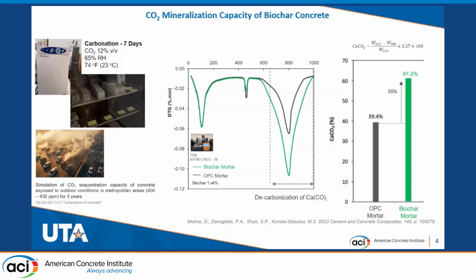And we assessed the carbon mineralization capacity. We followed this carbonation regime, this exposure concentration of CO2, to mimic the CO2 sequestration capacity of concrete exposed to outdoor conditions in metropolitan areas for approximately 3 years. And the CO2 sequestration was assessed through TGA tests. Using the weight-temperature data from a TGA test, we determined the percent amount of calcium carbonates by quantifying the weight loss between the temperatures of 525 degrees Celsius and 900 degrees Celsius, which is the temperature range for decarbonization of calcium carbonates.